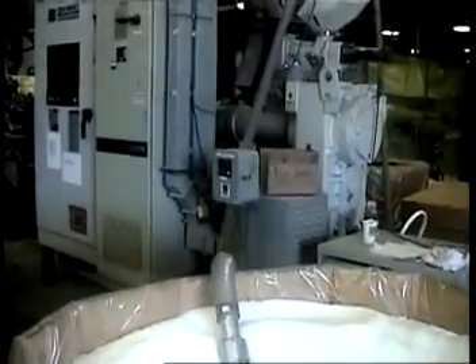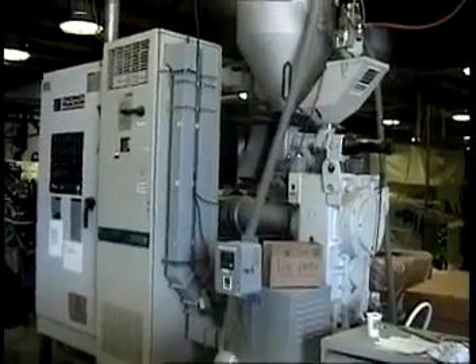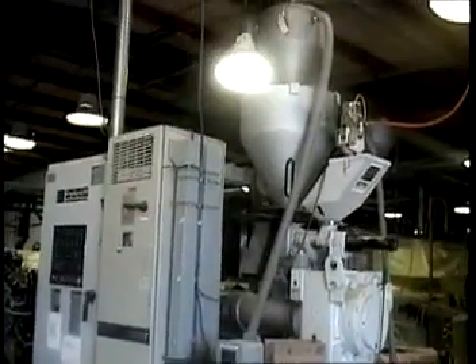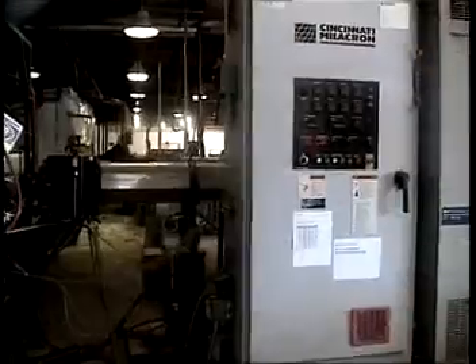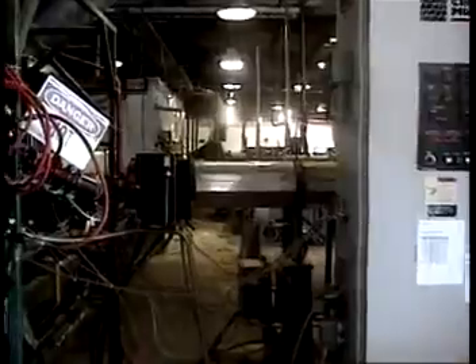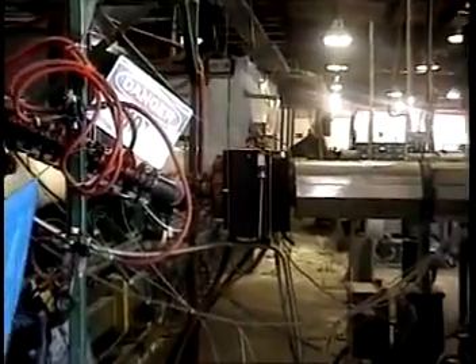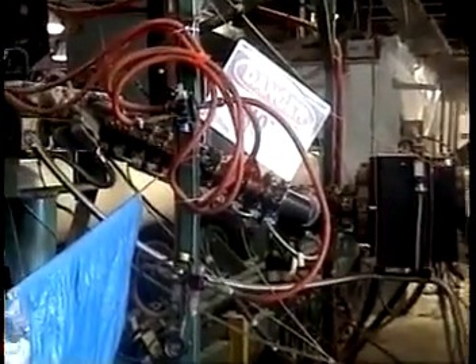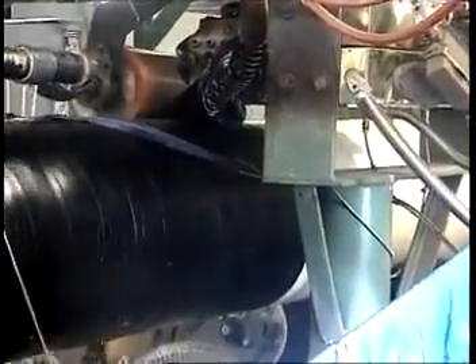The next step in the process is the polyethylene extruder. It is a Cincinnati Milacron 90mm extruder with 300 horsepower drive. The polyethylene material is fed automatically into the feed hopper and color is added automatically through a screw auger. The molten polyethylene is applied to the foam in a thin film at 435 degrees Fahrenheit.